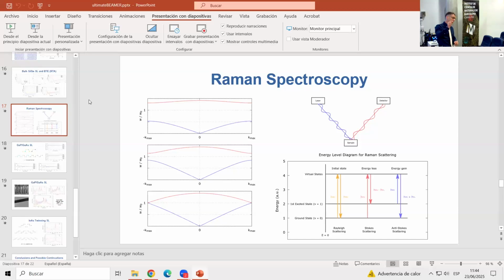If we could shine single photons into the sample, maybe, but I would say that we are just probing the zero momentum zone of the spectrum, because we are exciting just the bulk material. So the phonons that we excite inside of the material are completely delocalized. We are just exciting the oscillations of the primitive cell, but there is no modulation of the specific phonon mode along the superlattice with the current technology. It's kind of a more intrinsic limitation. It depends on momentum conservation and the momentum that the photons deliver. Yeah, of course. You would need heavier particles to reach the edges of the Brillouin zone.